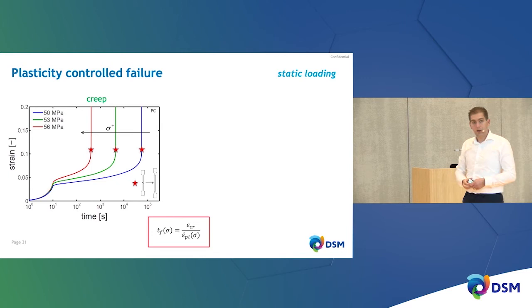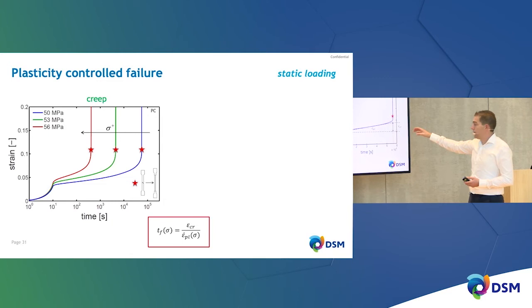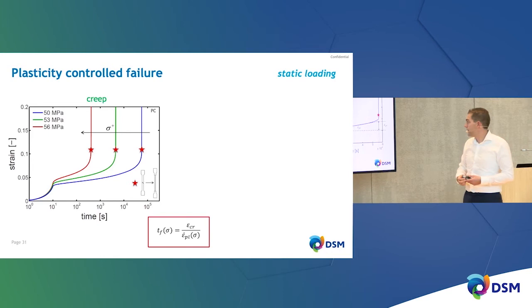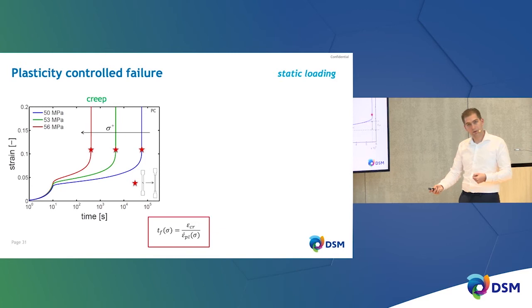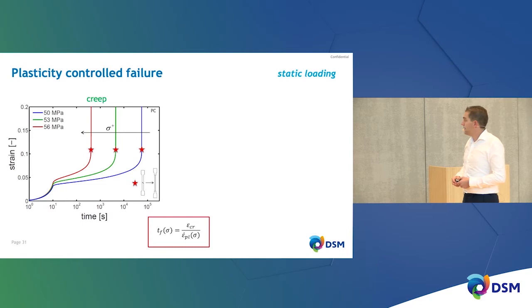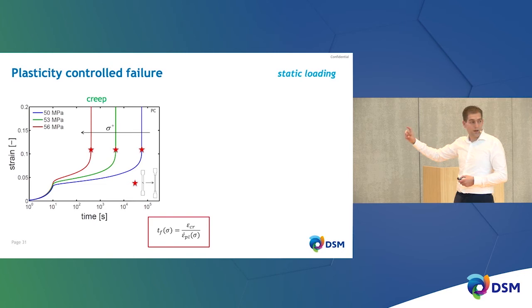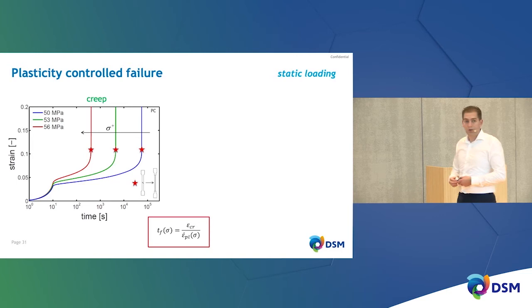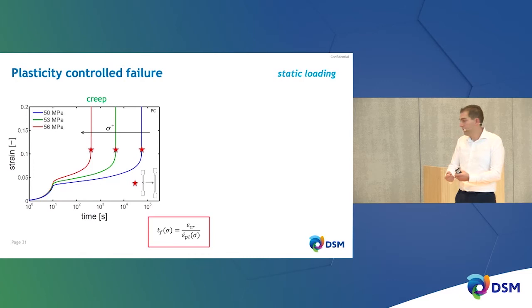A convenient phenomenological observation: if you multiply the lifetime by the secondary plastic flow rate, you compute a kind of critical accumulated plastic strain. Doing this for different loading conditions, only the creep rate changes — the critical strain that triggers failure remains the same. This tells you how to compute lifetime: you need to know the critical strain (how much deformation is allowed before failure) and the speed of deformation, which is purely mobility-driven — a function of stress — and this is something you can model.